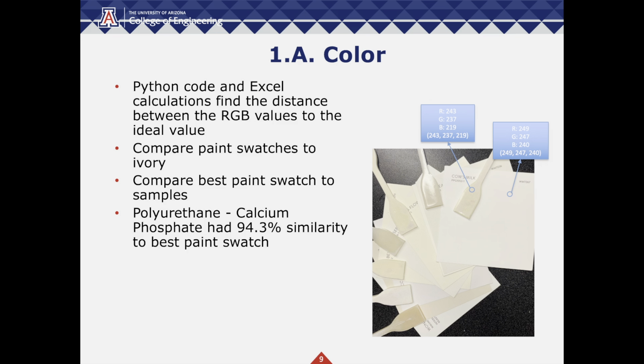The most important characteristic was color. We originally wanted to qualitatively check the color for similarity using paint swatches, but we decided to quantify the color comparison for more precision. To do this, we used colors' RGB values as points in 3D space and calculated the distance between each color using Excel and Python. We compared our paint swatches to standard ivory and then our ideal paint swatch to our samples. The optimal samples in our initial testing were the polyurethane and calcium phosphate mixtures with a 1-to-1 mass ratio.